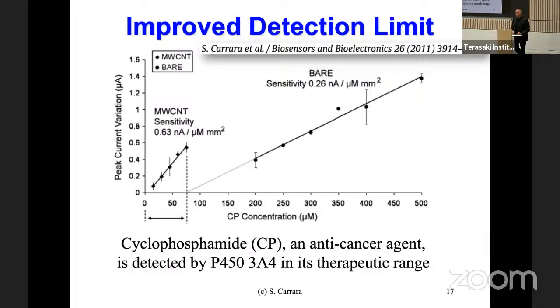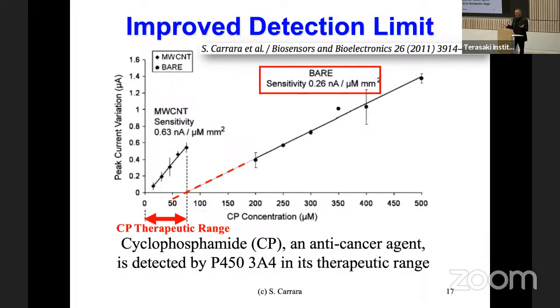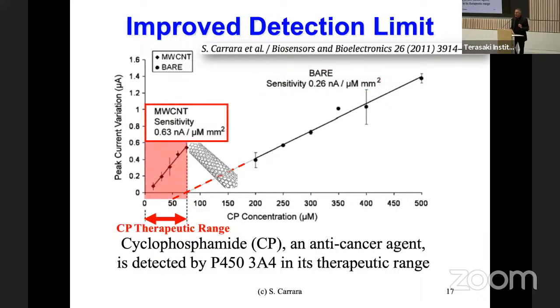But this is repeated for many other compounds. This is the case of cyclophosphamide, a very well-known anti-cancer compound detected by exactly the same isoform of the cytochrome P450. You see, if I try to just use the enzyme, I have a linear calibration, but the calibration exactly starts when the therapeutic range ends. So again, I'm too blind for a real application. But if I introduce multi-wall carbon nanotubes in my interface, I fairly well succeed in targeting the concentration in the patients. We have tried and repeated with ftorafur, etoposide, and other anti-cancer drugs, and it always works. So you see, in this case, carbon nanotubes brought us back in business with respect to a real application.